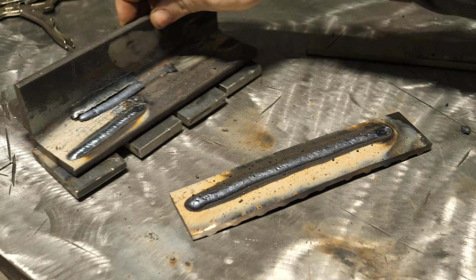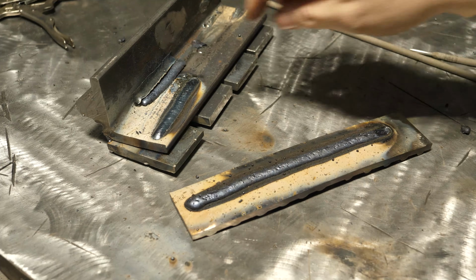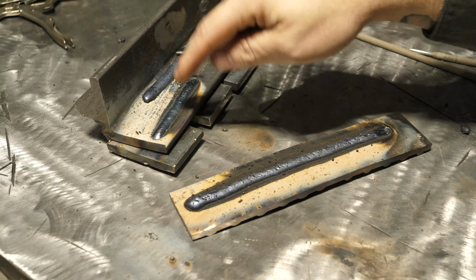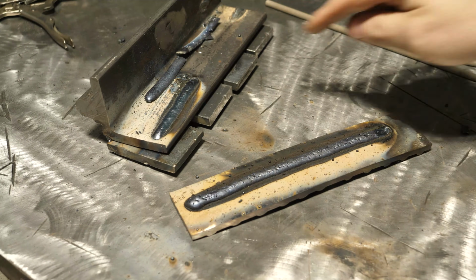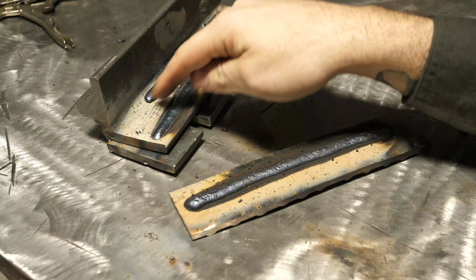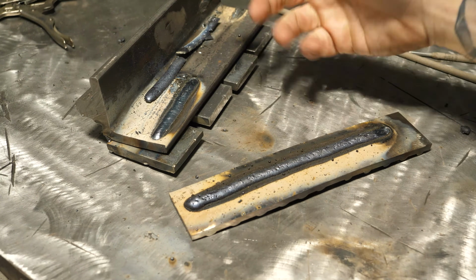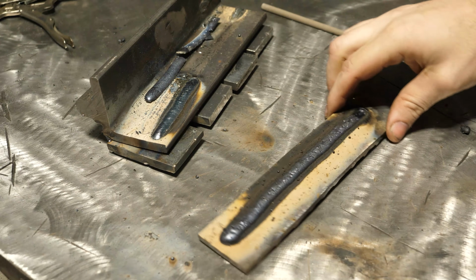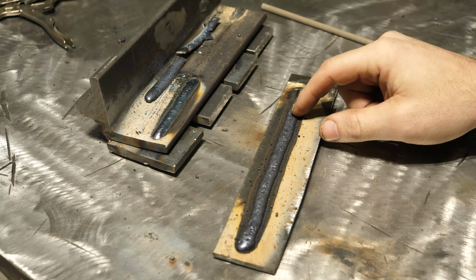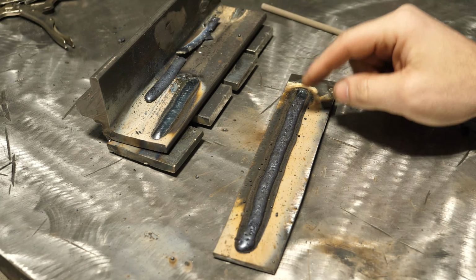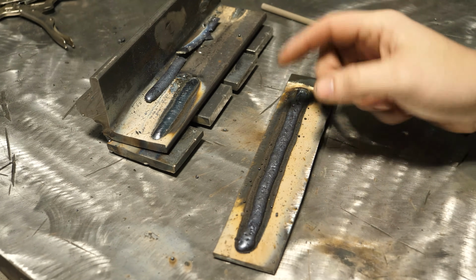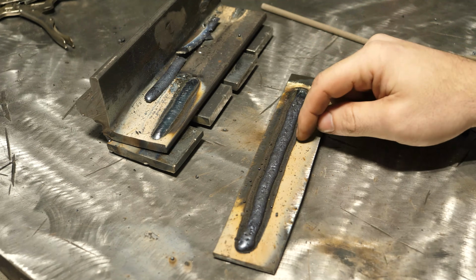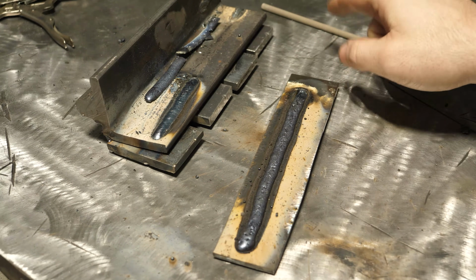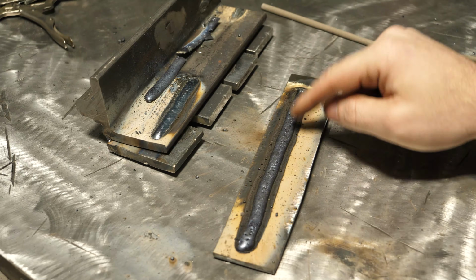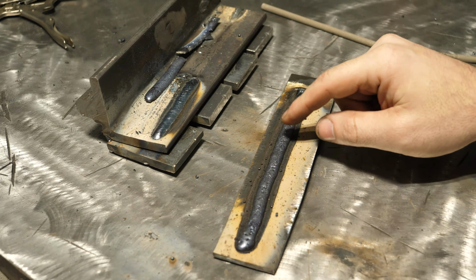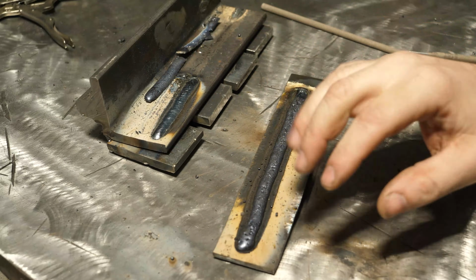All right, as you saw in the arc shots, when you get everything right, and man, that's a little hot still, you get banana peels off of it and awesome looking welds. I didn't clean the dust up on that, but you can see it pretty much looks like chrome. Now on this guy, I would say I was running 150 amps, a little bit too hot for this particular rod. I'm used to running Lincoln's jet rod, which tends to take a little bit more than this Blue Demon seems to, but once I dropped it to 140, that's what I ran these two at, ran perfect.